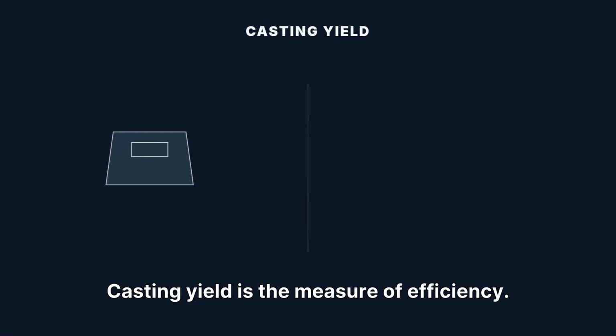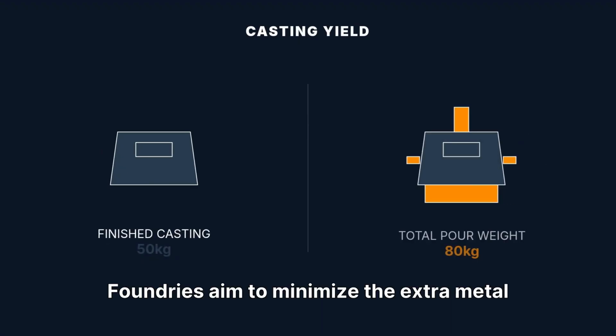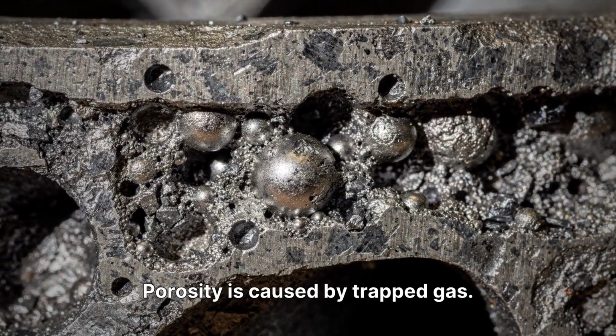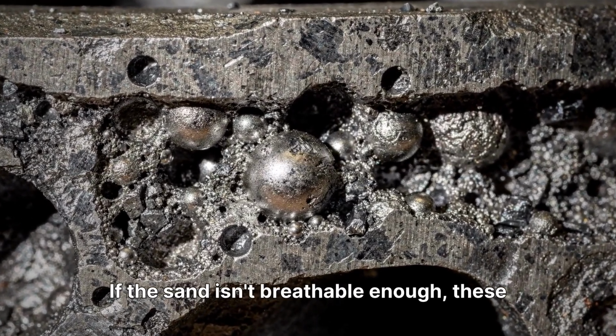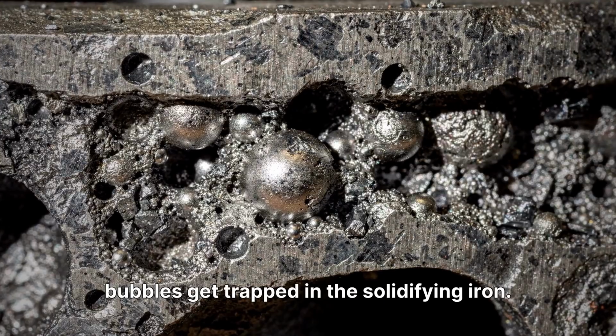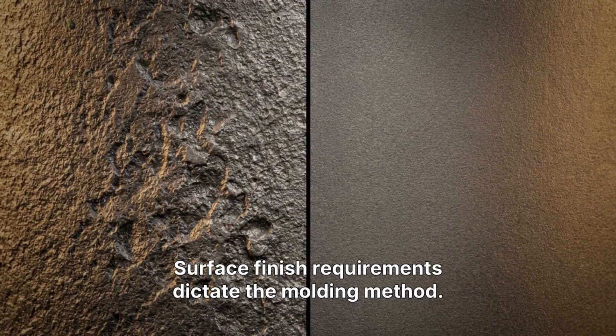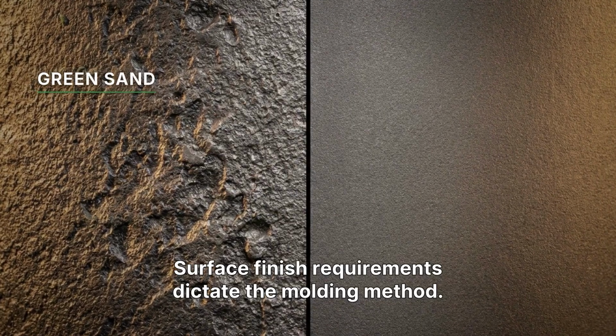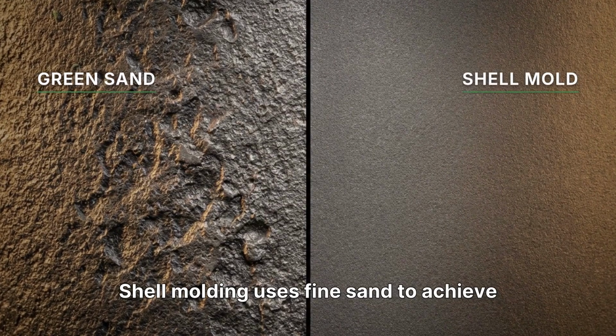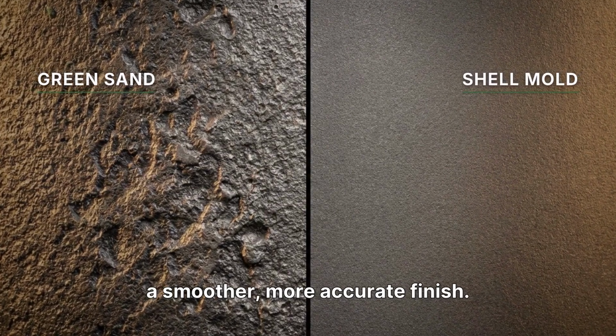Casting yield is the measure of efficiency. Foundries aim to minimize the extra metal used in the gating system. Porosity is caused by trapped gas. If the sand isn't breathable enough, these bubbles get trapped in the solidifying iron. Surface finish requirements dictate the molding method. Shell molding uses fine sand to achieve a smoother, more accurate finish.